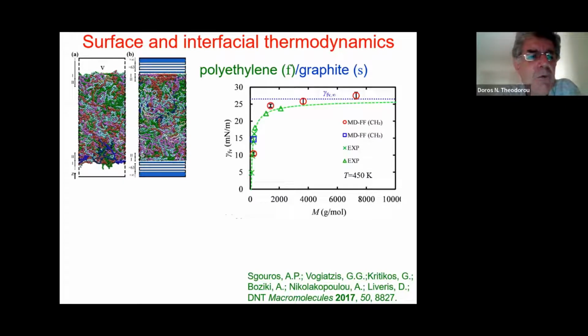Now, from a well-equilibrated simulation, Monte Carlo or molecular dynamics, you can actually calculate the normal and tangential transverse stresses in the interfacial regions, and via the Irving-Kirkwood or the Harasima expression, you can calculate the surface tension for the melt or the interfacial tension. And here, for example, are the surface tensions of this free film as a function of molecular weight at 450 Kelvin, based on the TraPPE force field and the Steele potential for, well, rather, there is no graphite here, it's just the polymer. And you can see that the surface tension rises with increasing molecular weight. The simulation points are the red and the blue, and that is as also seen experimentally.